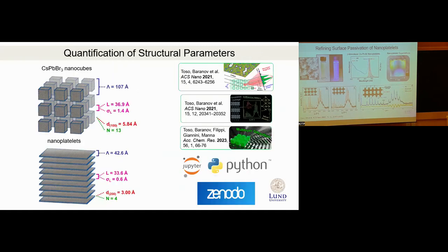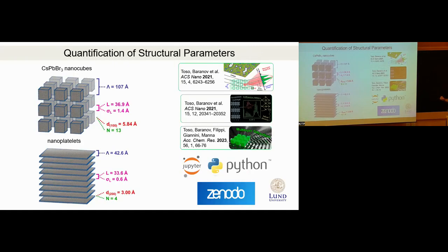So to wrap up this part, what we achieved and learned about this material is that it's very well ordered, and we developed these techniques for superlattices of cubes and nanoplatelets, with the code and raw data available as part of the supporting information. The Bawendi group recently used it for synchrotron experiments on nanoplatelets as a function of temperature. Also, I think the Talapin group used it to characterize changes in nanocube superlattices after ILD. Two people who do theory and simulate the dynamics of superlattice formation. If you start making your codes available, then experimentalists might start trying to use them for their systems, and that maybe will accelerate the progress.